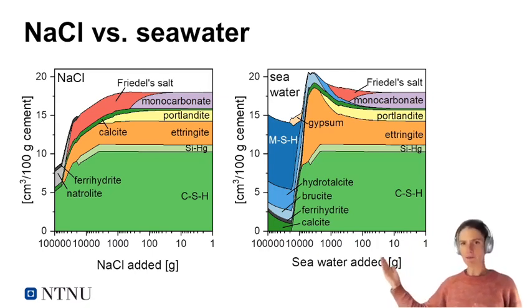And if you add even more seawater to our system, we're forming a lot of these blue phases, which I've used to mark the magnesium-rich phases. It could be M-S-H, brucite, hydrotalcite. So these we are expecting to form when we're in contact with a high volume of seawater, so at the surface.